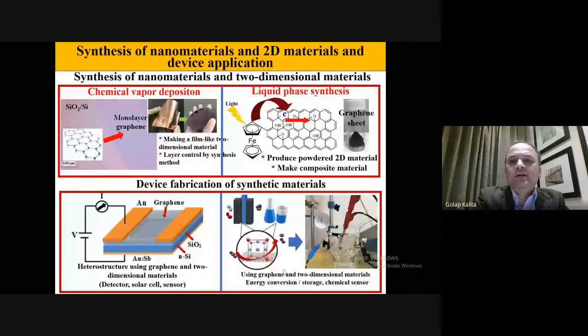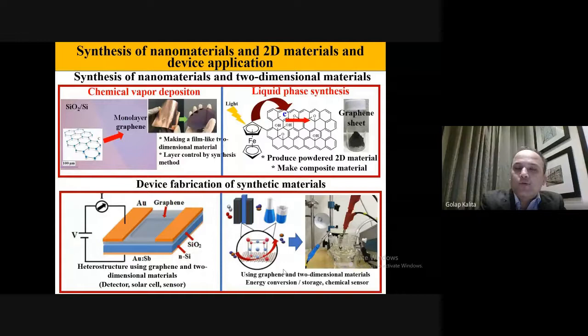What we generally do in our lab is a lot of work on chemical vapor deposition. Chemical vapor deposition is the CVD process. We can grow very high quality monolayer graphene. Monolayer graphene is one atom thick layer of carbon atoms. One carbon atom thick layer is around 0.34 nanometers of thickness. So you can see that it is the thinnest material you can synthesize.